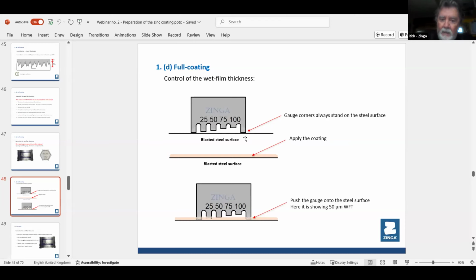So here, that pink is showing you the liquid zinc, okay? It's been pushed in and it's touching the tooth of 50 microns. So therefore, you know that coating is 50 microns wet. So if you do your calculations, you know that's going to dry around about 23, 24 microns dry using that little formula that you saw. So that's basically how these work.